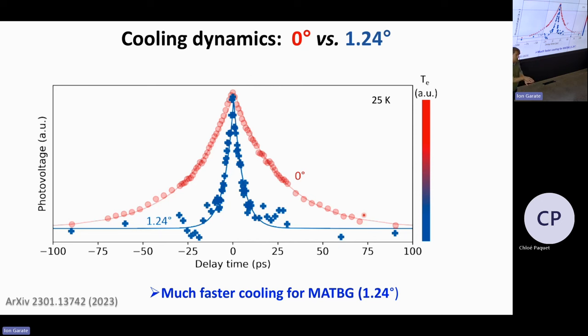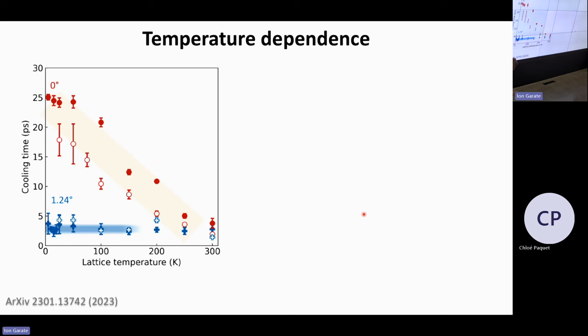You twist the sheet by 1 degree, and suddenly you get picosecond cooling, so much faster. So that's quite striking. So we wanted to understand that better. So we looked at the temperature dependence. And what you see is that at room temperature, they're cooling more or less equally fast. So it's like a few picoseconds.